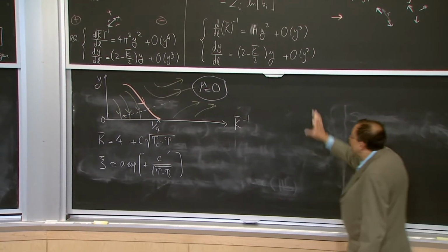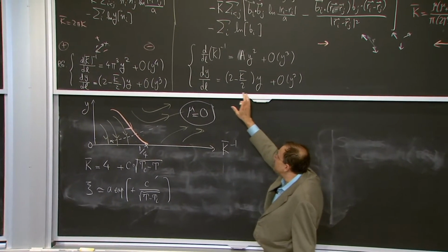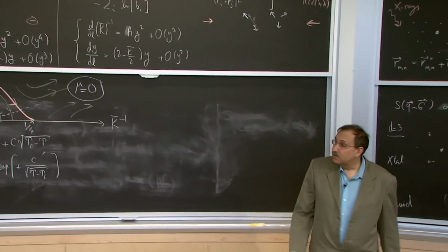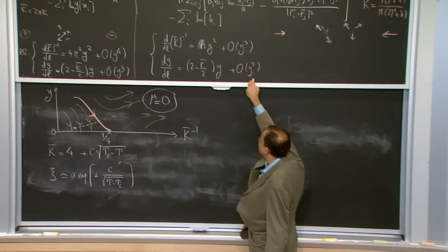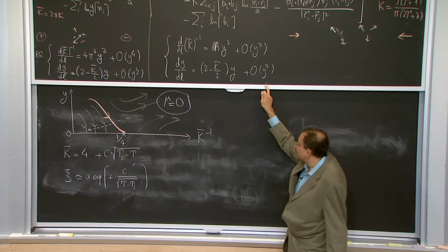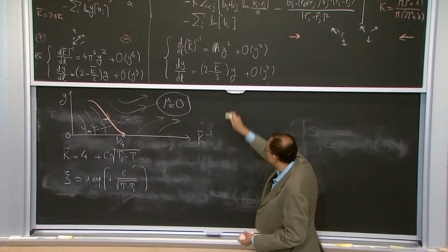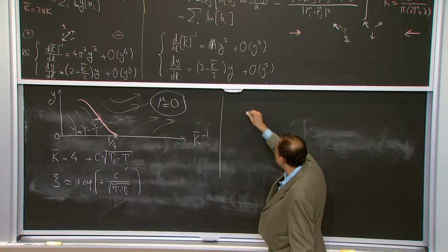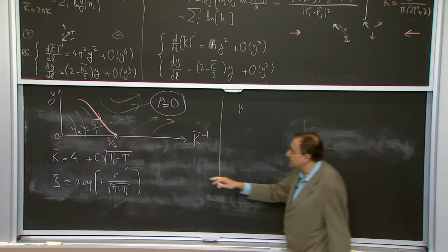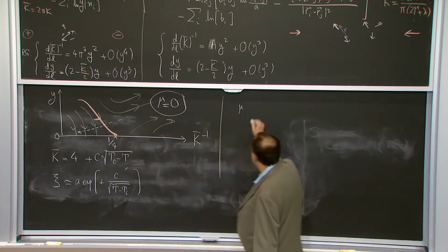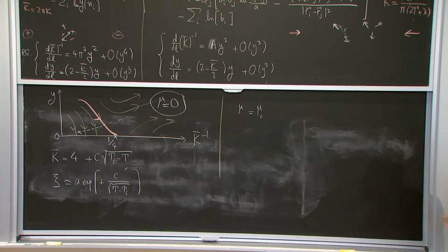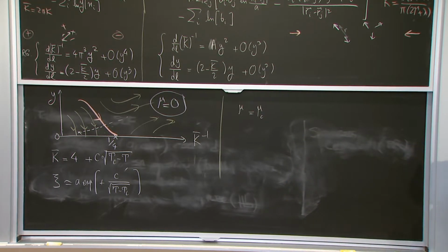While everything kind of looks identical between this RG and the other RG, it turns out that once you keep track of these corrections, they are actually important. And for the vectorial version of the Coulomb gas, you find that the shear modulus that is finite in this phase reaches its final value, which is not universal, because the thing that is universal is that combination that involves both mu and lambda.